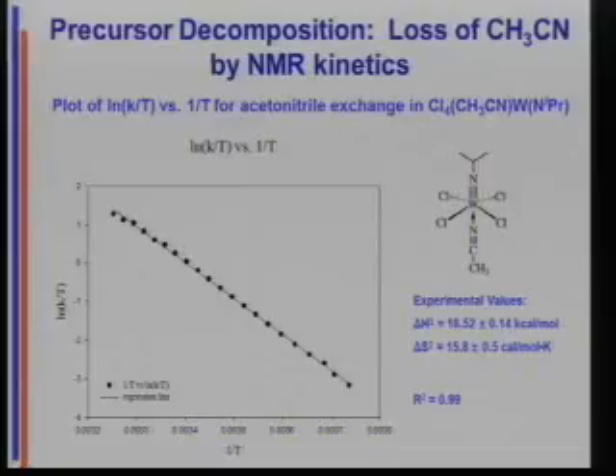Let's check it out. And here's where my group starts doing mechanistic chemistry. Before I ever give a precursor to a collaborator, I do as much pre-screening as I can. So we do as much mechanistic work, asking ourselves, what is the decomposition of this going to be like? Here's this molecule that I just showed you. And these are NMR kinetics for loss of acetonitrile. Actually it's acetonitrile exchange, but it's dissociative exchange because delta S double dagger is positive. So I'm looking at acetonitrile loss.